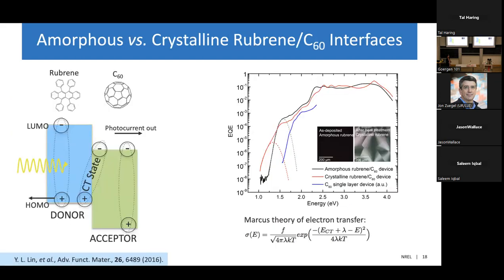Now, to actually build our solar cell, we need to introduce an electron acceptor. We're using C60 as our electron acceptor. So here I have the HOMO and LUMO diagram for the resulting solar cell. And both the rubrene and the C60 can individually absorb light. And then you can also absorb directly into the interface between the donor and the acceptor. And this results in a low energy absorption feature beyond the spectra of either rubrene or C60 by themselves.